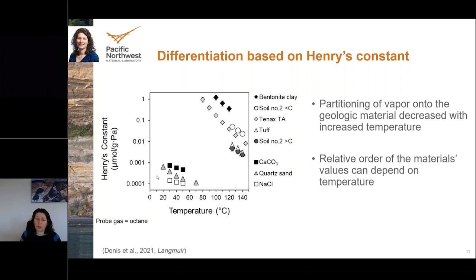If you have a larger Henry's constant, that's indicating a greater affinity or absorption of a gas for a material relative to another gas with a smaller Henry's constant. Based on our results, we were able to differentiate between the materials, and you can see that for all the materials, they have that downward trend where the partitioning of the vapor on the material decreased with increased temperature, which is what we'd expect, that at higher temperatures, you're favoring more being in the gas phase rather than absorbing